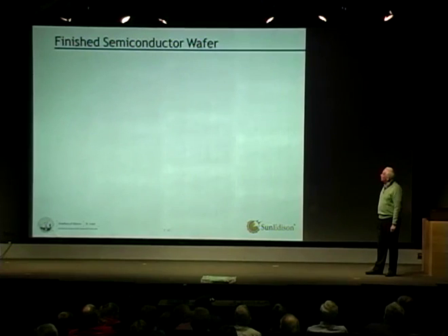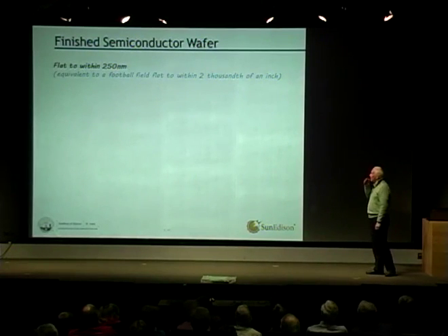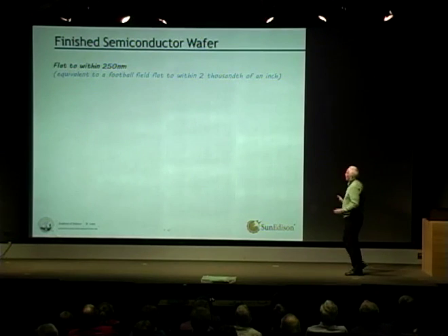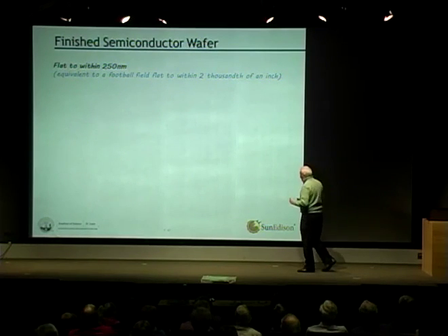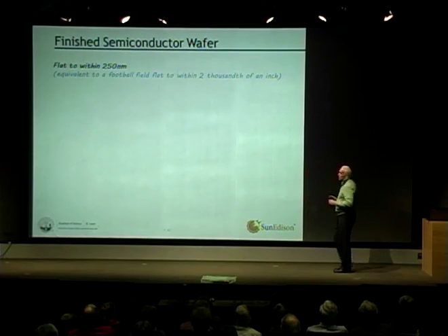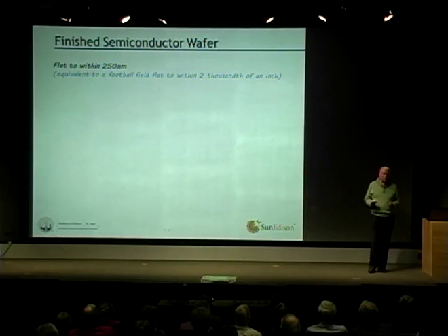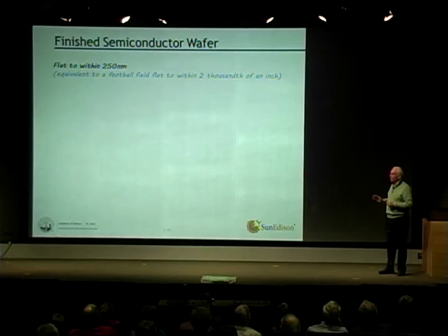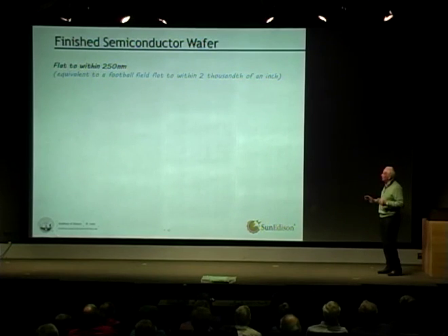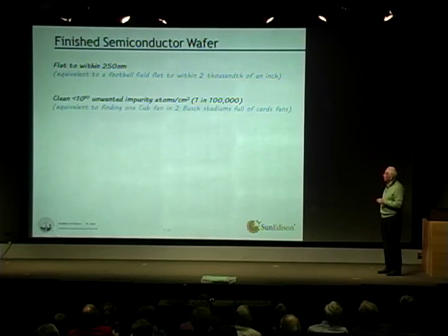Okay, so when we get these finished wafers, just to give you an idea, it's flat to within 250 nanometers, but that's equivalent to making a football field flat to within 2/1000ths of an inch. Now, in practice, of course, you can't make a football field flat to within 2/1000ths of an inch, so it's not exactly equivalent, because we can make the silicon wafer that flat. But if you were to scale it up, that's what it would be equal to.